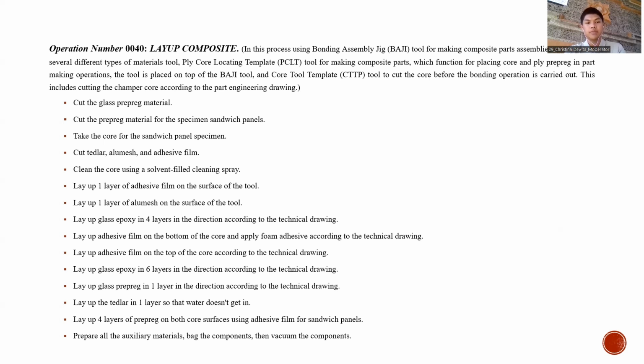Lay up adhesive film on the top of the core according to the technical drawing, and then lay up glass epoxies in 6 layers in the direction according to the technical drawing, and then lay up glass pre-preg in 1 layer in the direction according to the technical drawing, and lay up the Tadlar in 1 layer so that water doesn't get in, and then lay up 4 layers of pre-preg on both core surfaces using adhesive film for sandwich panels. Prepare all the auxiliary materials, bag the components, then vacuum the components.